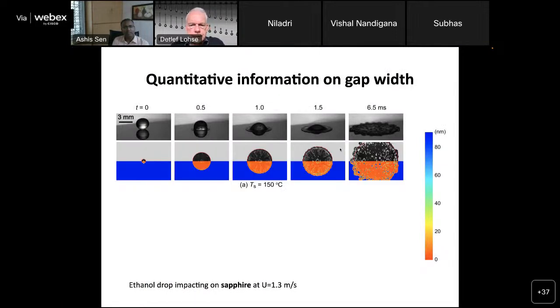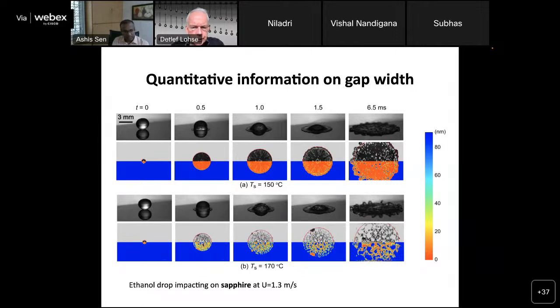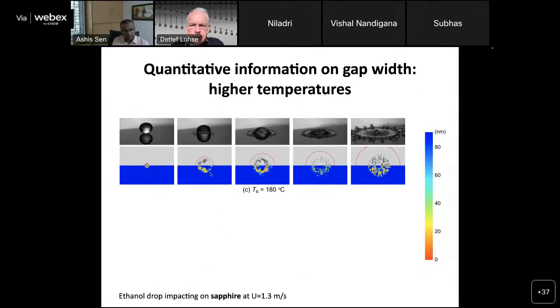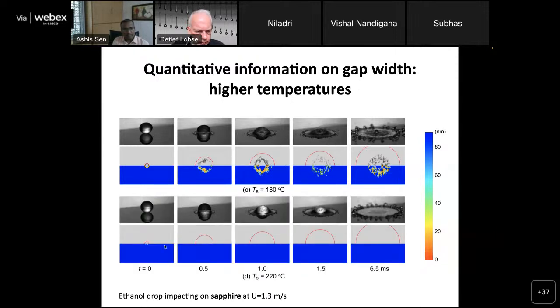So here you see milliseconds, and in the first moment there is some more contact than later here. In the very first case, this is milliseconds, you see some contact right here, and later this is gone. So in the very first moment there is contact, a little bit more contact, then it's evaporated. This is in fact on a time scale smaller than 1 millisecond. And then later it's evaporating and you don't see any contact anymore.